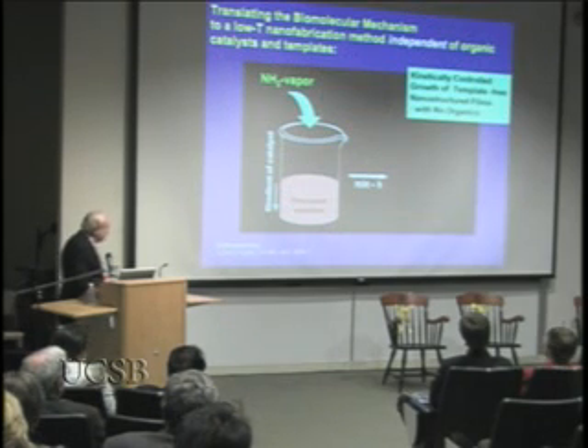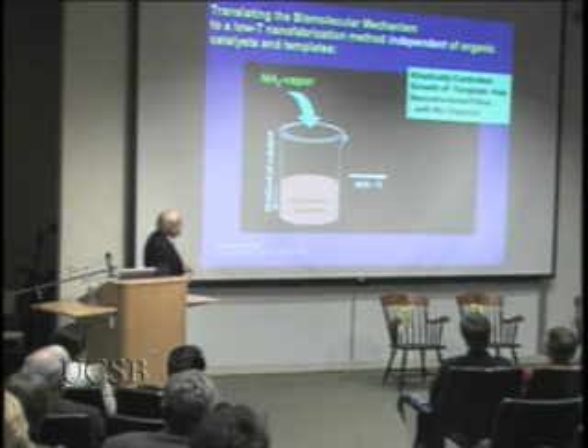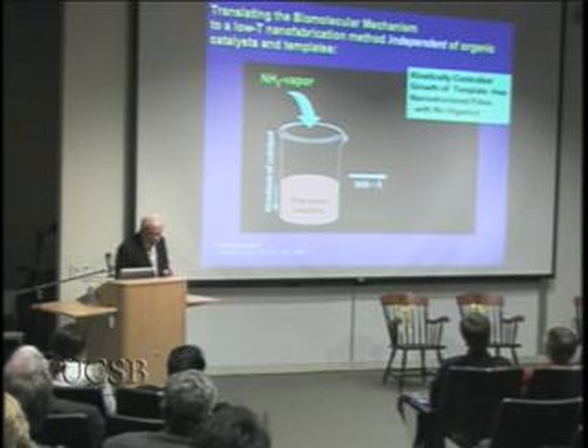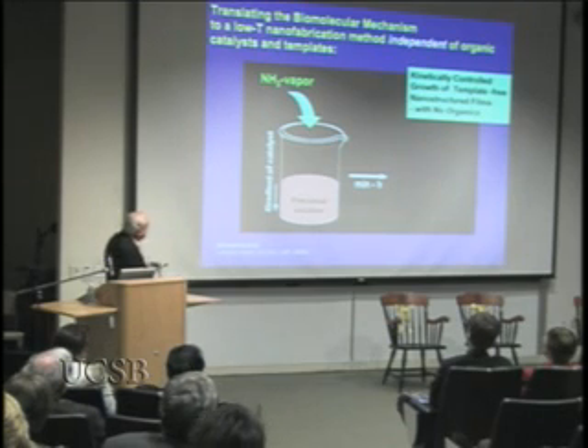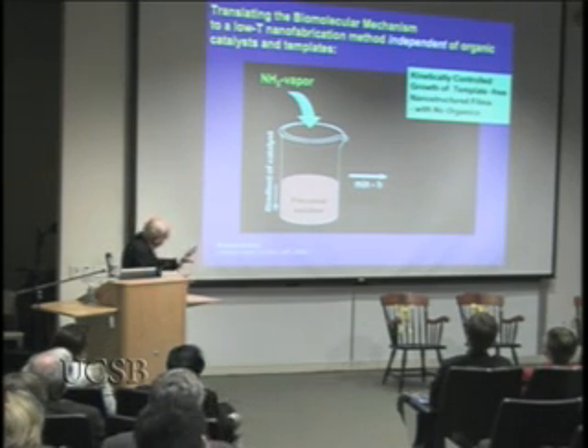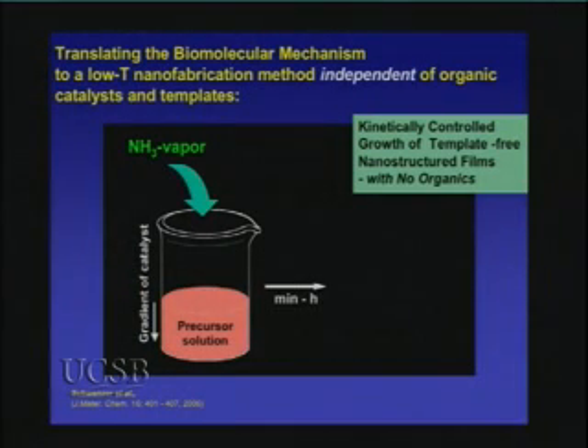Well, a template, we realized, is just another means of vectorially controlling the growth of the crystal in space and in time, anisotropically structuring the reaction environment, if you will, imposing spatial constraint on the growth. And so this can be useful to regulate the kind of crystal, its orientation at an atomic level. We developed a generic approach to accomplish both of these things, as illustrated here. This is highly generic. I'll illustrate it just for the simple hydrolysis chemistry that was the basis of the silica and metal oxide formation.